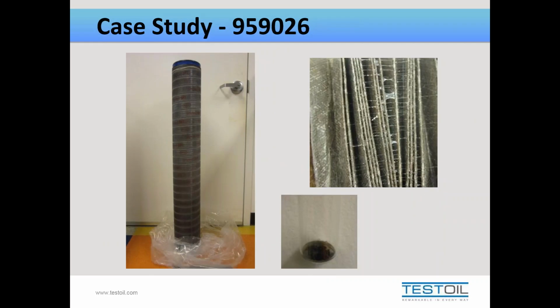So while we get some pretty small filters here for testing, we also get some pretty large filters, as you can see here. This one's halfway up the door. This one's actually a diesel fuel filter that came in with a sticky resin, which you can see really well in that top right picture. And these filters were plugging within 24 hours. And I was told by the customer that they were using 1 gallon of additive for every 1,000 gallons of fuel, which worked out to be a concentration of 0.1%.